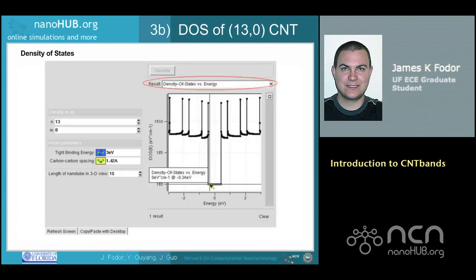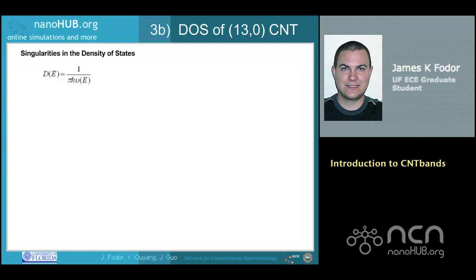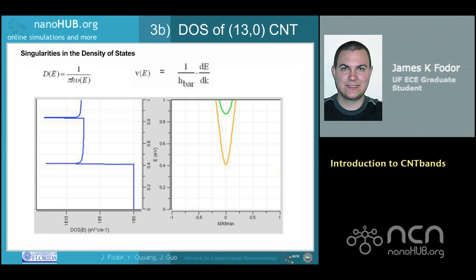For part B, select density of states versus energy from the results pull-down menu. As expected, the CNT is semiconducting, so the density of states near the Fermi level is 0. There are singularities near the subband gaps. The density of states is inversely proportional to the velocity of carriers, so when the carrier velocity is 0, a singularity in the density of states will occur. Since velocity is directly proportional to the derivative of the E-K relationship, when the E-K relationship has a maximum, minimum, or point of inflection, a singularity in the density of states will occur, as verified by examining the E-K plot.